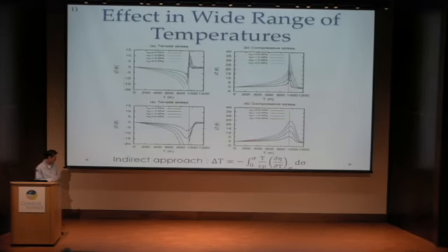Let's go right here. We see in the indirect approach we have this initial temperature term here, so you would definitely think that it's going to have a strong effect. In our calculations using the adiabatic Monte Carlo approach, it affects the value, but it's not overly significant. It's not the reason why we're getting these large changes in temperature. The large changes in temperature come from the fact that multiple order parameters are being distorted by the mechanical deformation of the system. This is what we're postulating as the reason for these large changes in temperature. It doesn't necessarily correspond directly to us having a high Curie point.